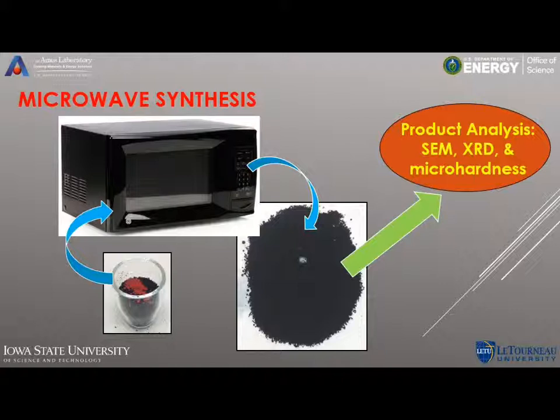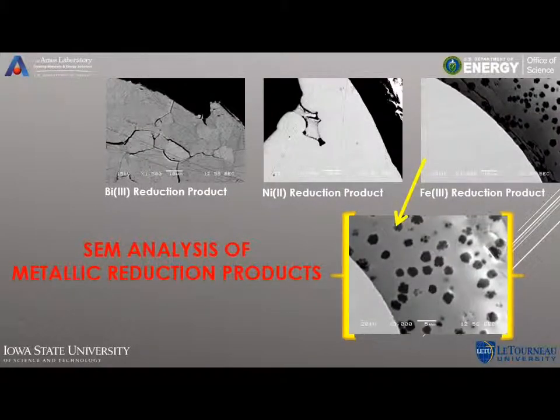Now, the first summer, 2013, was when we focused on making the microwave reduction products. This second summer, summer 2014, or just the last summer, we focused more on the analysis. Here are some SEM images of the bismuth-3, the nickel-2, and then the iron-3 reduction products. And I could tell in looking at these, after running also elemental analysis, that there's pure metal here that's been formed. You can tell, especially when you look at backscatter, because the metal shows up really bright, whereas you have this dark background for the mounting material, which is mostly carbon. So it shows the difference in density of the atomic character.